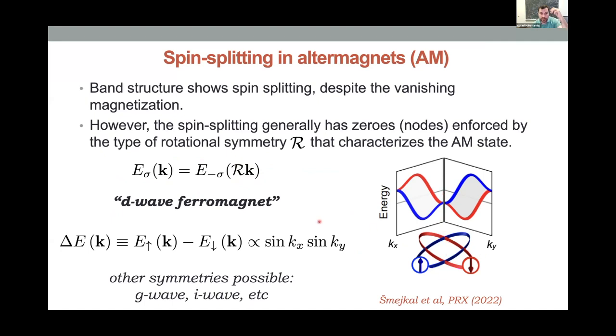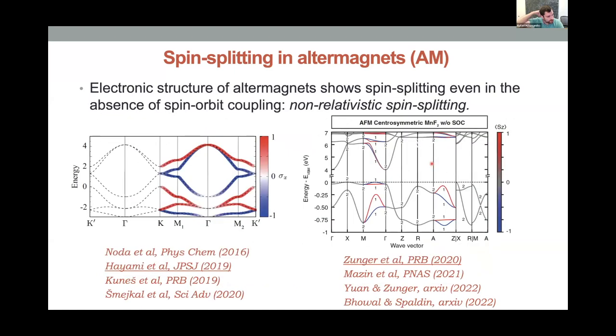So in general, you'll get some sort of nodal spin splitting structure. It could be a D-wave form factor, but as pointed out, could also be G-wave, I-wave. Any even parity modulation can happen. And again, this follows from the symmetries of the system. And one of the appeals of this idea was the fact that it realizes what's called non-relativistic spin splitting. There are previous works that also have pointed out that this could happen in specific materials.